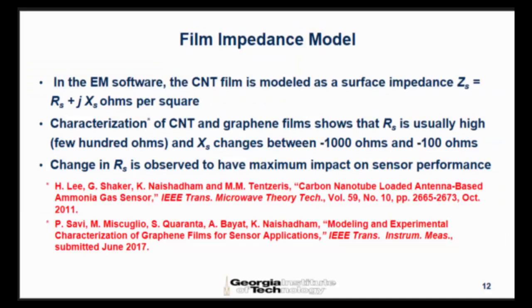In the model, we use a surface impedance for the CNT film. And we did extensive characterization of CNT and graphene films at microwave frequencies, and it's reported in these two papers. We found that the resistance usually is a few hundred ohms, and the reactance changes by a small amount. So the surface impedance is primarily dominated by the resistance, which one would expect for a carbon material, correct? Carbon materials have high resistance. Their reactance is essentially because of parasitics and other things, but nanotubes themselves don't have too much capacitance. Their kinetic inductance and capacitance are small values. So we found that the change in the resistance can have maximum impact on the sensor performance.